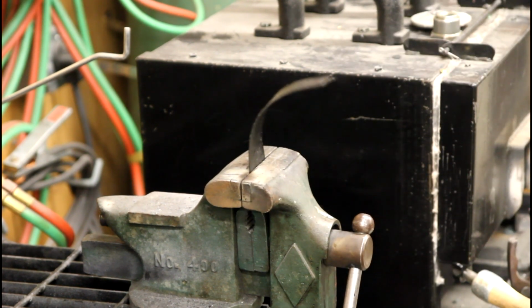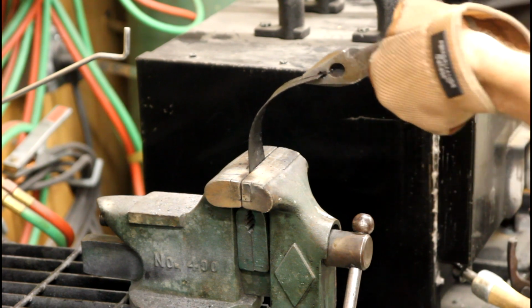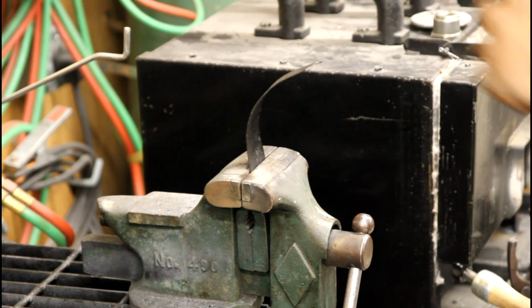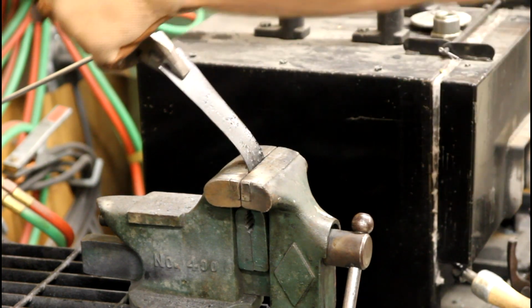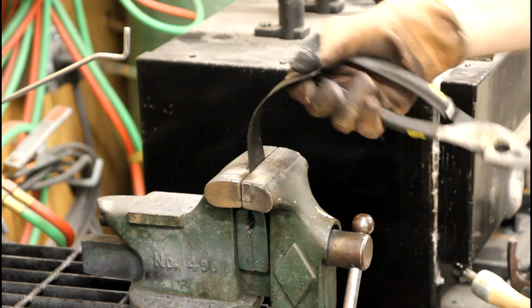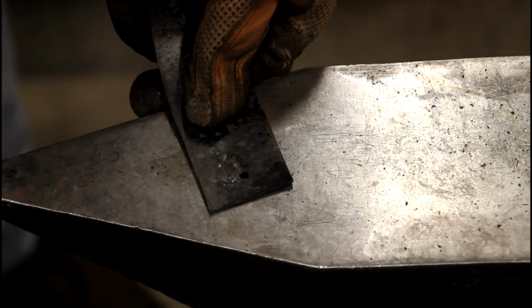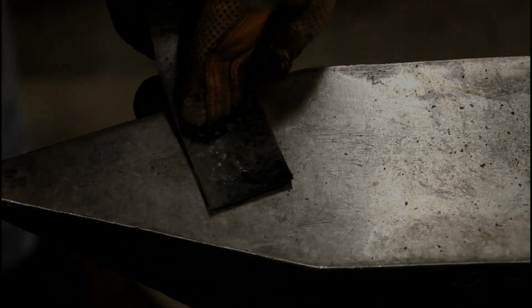This piece of tempered steel was given a soft temper, and as you can see, it's much more difficult to bend the piece, and more importantly, it springs back to its original shape, hence spring steel. When put on the anvil, the piece is much more difficult to deform than mild steel, but more importantly for armor, it does not crack.